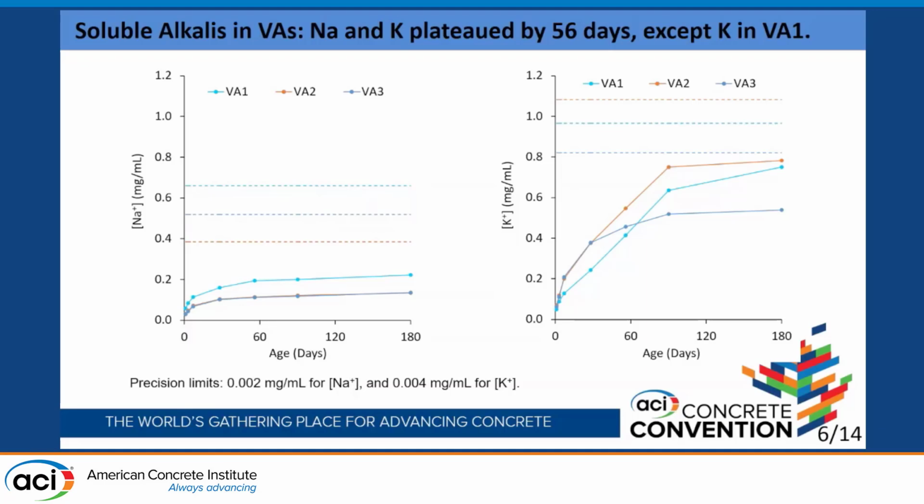For the majority of the SCMs, the soluble alkalis plateaued at 56 days. But it wasn't the case for all of them. An example, again, is VA1. The soluble potassium continued to increase up to 6 months. I won't present all the results in this format for all the 14 SCMs, but I will present them in the format of percent weight,